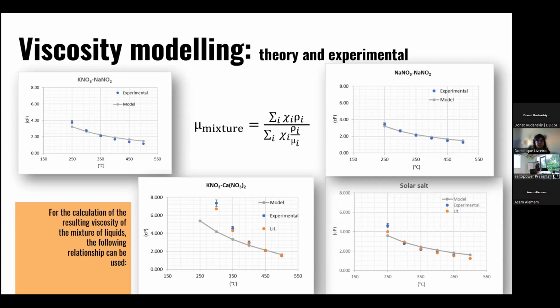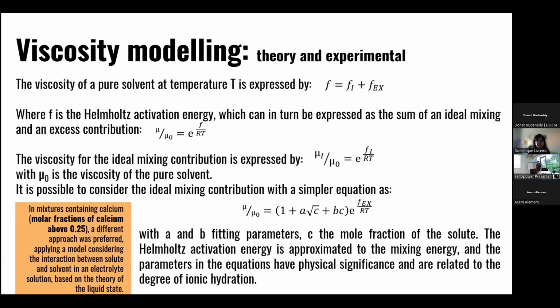That is a comparison between the experimental data and the modeling. And as you can see, there is a good accordance for, for example, potassium nitrate and nitrite, and sodium nitrate and nitrite, and for the solar salt, but not with mixtures containing calcium. So for mixtures containing calcium, we preferred to use a different approach.